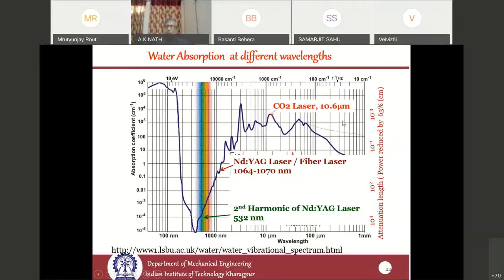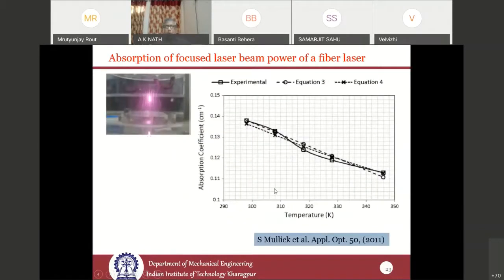CO2 laser has got limited applications, but as I go along, I will tell you how this has been exploited for use. In IIT Kharagpur, we have also tried to find out how the absorption of the fiber laser takes place when we focus the laser beam, because when the laser intensity at the focal point is very high, certain nonlinear effects take place and the water gets heated up. So we have tried to find out how, along with the temperature rise, the absorption coefficient goes on reducing.